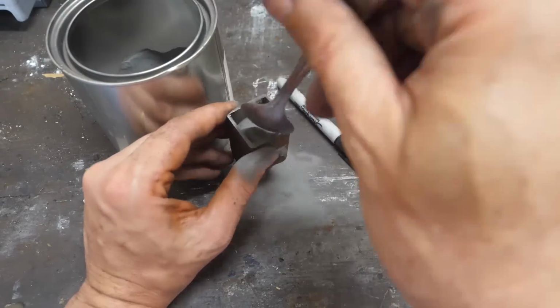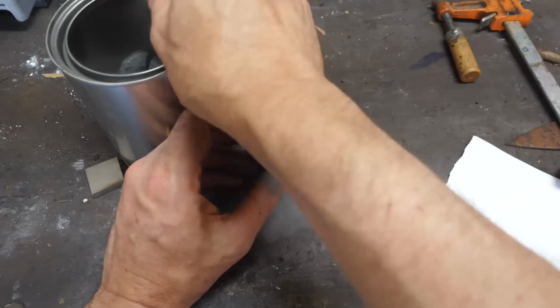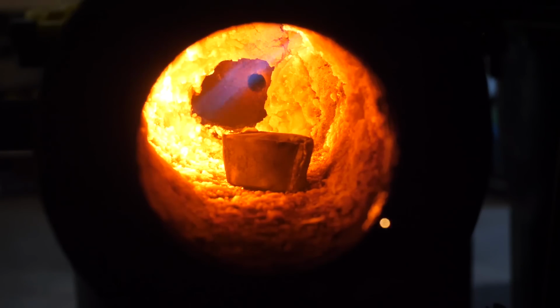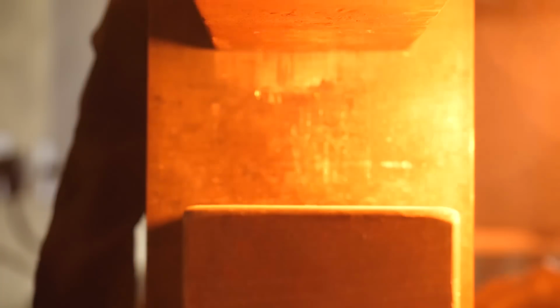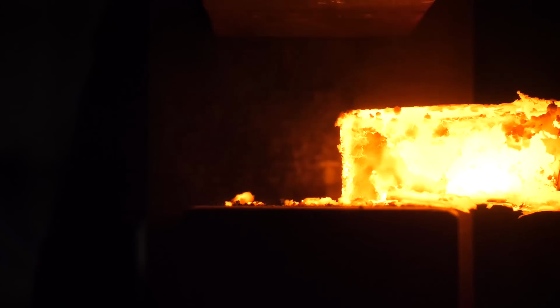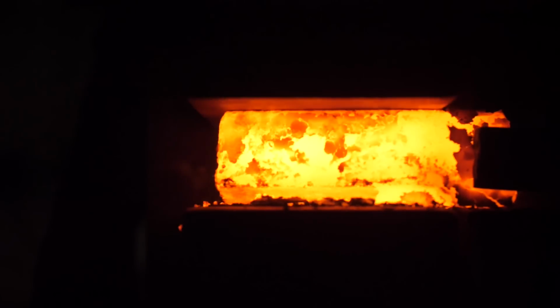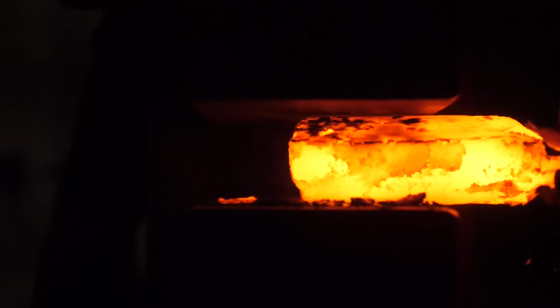But to get our welds to stick together better, I'm going to flatten this piece back out, put it in a canister, and press it at welding temperatures. We added powdered steel to the canister just to make sure there's as little oxygen there as possible. That's why we put paper in there too, to consume any oxygen that was in there. Remember, oxygen is bad for forge welds.